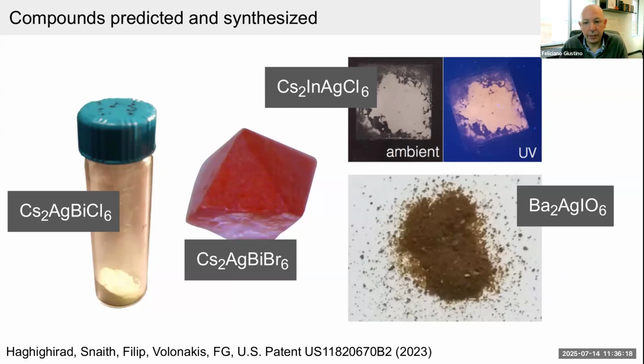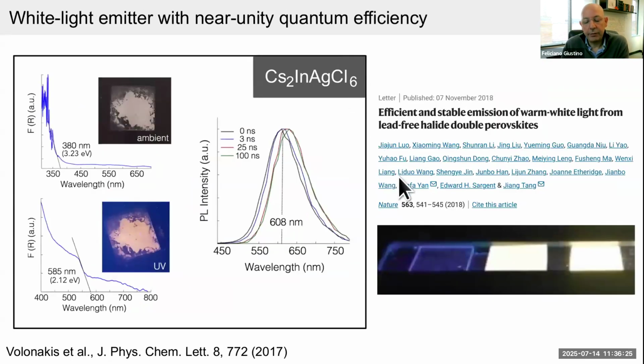Maybe the most striking result is that for this one that originally was really maybe the one that we had the least hopes, just 1 year after we made the prediction, the group of Jiang Tang actually demonstrated that this compound can be made in extremely high-performing LED devices. In practice, this compound emits warm white light with near unity quantum efficiency, and therefore it can be used to make LEDs where you don't need to combine red, green, and blue to get white light, but you have a single material that already produces white light by itself.